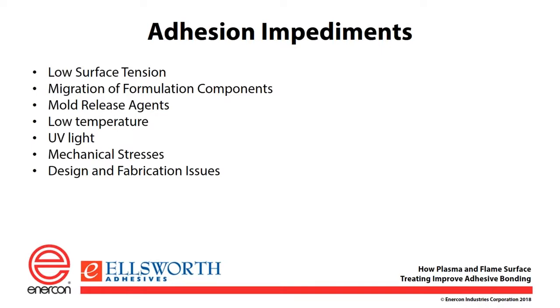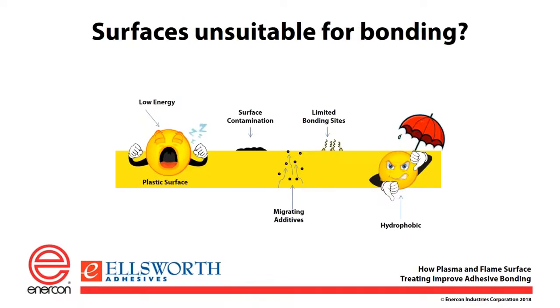So the surface of the material that you're trying to bond is critical, as mentioned before, and we're going to look at those in the next two slides. If you have a hydrophobic surface, you have low surface energy. You might have contaminants on it. There may be migrating additives such as flame retardancy materials that are put into the resin. You might have fluoropolymers in there that like to switch positions on you during the life of the material, and these cause limited bonding sites, and you're going to have a poor bond.